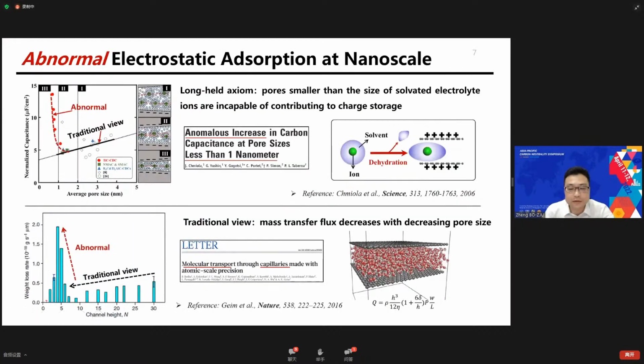Such an abnormal feature has attracted great interest, including not only ion adsorption, but ion and water transport. The most important reason is that the transport and adsorption occur in the nanopores, the so-called nano-confined spaces. The pore size is close to the diameter of ions and water molecules, which calls for a deep understanding of the electrostatic adsorption mechanism at nano-confined spaces.